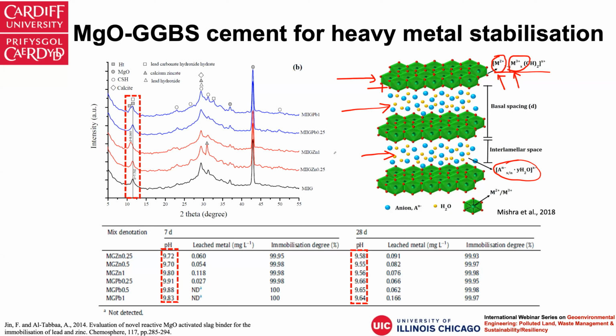That has been demonstrated in one of my studies of using Magnesia-GGBS cement to treat high concentrations of zinc and lead. If you look at the X-ray diffraction for the high zinc sample, you can see the shift of the d-spacing, indicating the incorporation of zinc into the crystal structure of this hydrotalcite or LDH. Another benefit is that this LDH has a high pH buffering capacity. After the TCLP leaching, you can see that the pH is buffered at around 9 to 10, which again is almost the optimum pH for precipitating various heavy metals.